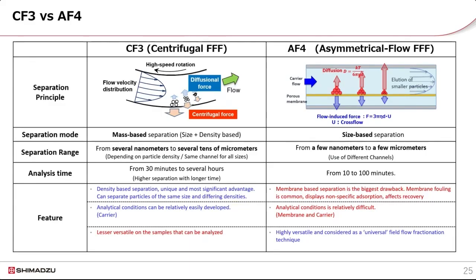As we all know by now, the separation on a CF3 is based on the differences between the masses of the nanoparticles. AF4, on the other hand, separates purely based on the size of the nanoparticles. The separation range for CF3 starts at about 10 nanometers and goes up several microns. For AF4, it starts a little lower than the CF3, and the upper limit is also a little lower than the CF3. The analysis time for the CF3 is 30 minutes to several hours, depending on the resolution that is desired and the nature of the sample. AF4 analysis is up to 100 minutes typically.